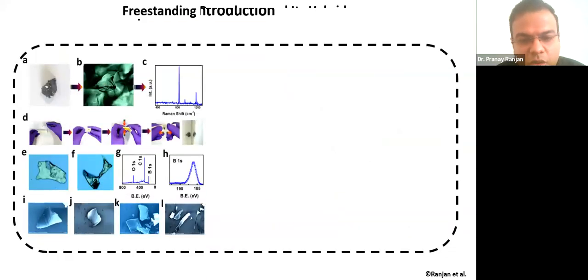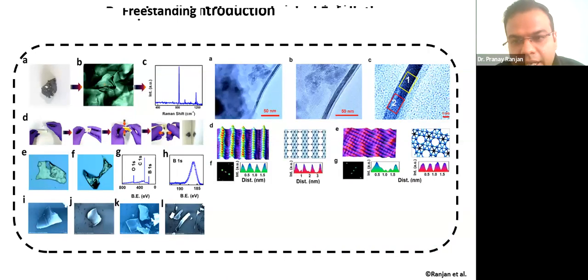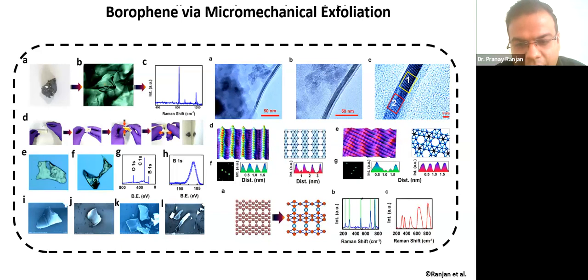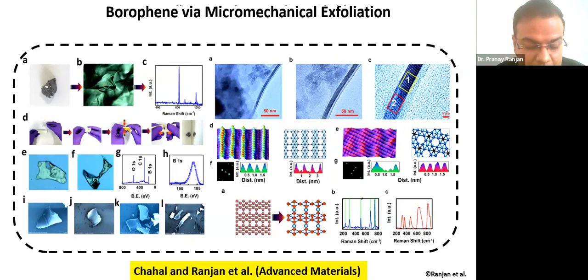Later on, I tried to exploit the same borophene through a new technique known as micromechanical exfoliation, and I ended up with the borophene sheet. Again, the hypothesis got broken that you cannot exfoliate borophene through micromechanical exfoliation. Looking into more detail, we again ended up with the beta 1,2 and the chi3 phase, which are the two 2D phases of borophene. When we did different spectroscopic investigations, we found that the phases have been made in the right phase and purity. This was again published in Advanced Materials.